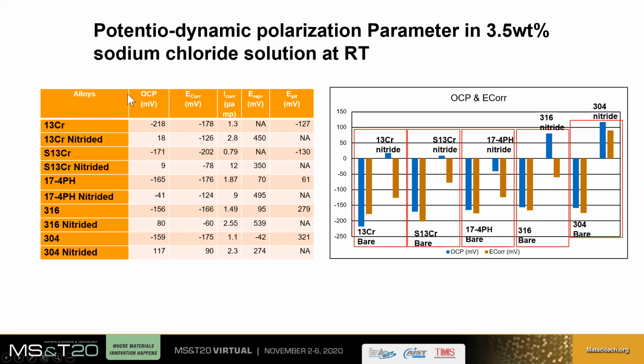This slide shows the electrochemical parameters extracted from the polarization plots I showed earlier, and this data is summarized in this table. We can observe that OCP and corrosion potential have improved for each alloy after nitriding treatment, and they have shifted toward the increased side, for 13 chrome, super 13 chrome and 17-4 PH, and for the other two alloys as well.